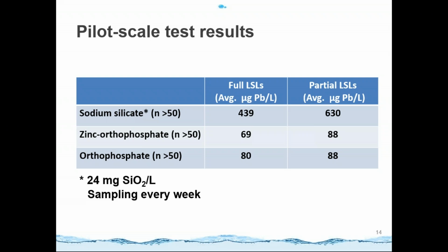The effluent from the partial lead service line pipe has a relatively higher lead concentration due to the galvanic reaction. In the orthophosphate treated system, the lead concentration was 88 micrograms per liter. However, the lead concentration in the sodium silicate treated system was 630 micrograms per liter.